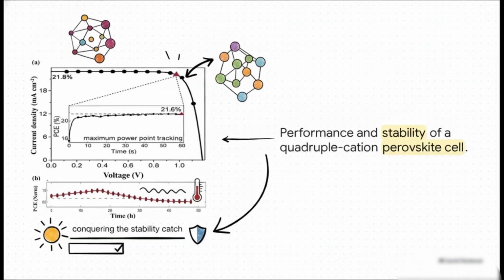And when you bring all of these techniques together, the results are nothing short of extraordinary. Testing a heavily engineered quadruple-cation cell, which basically just means scientists meticulously mixed rubidium, cesium, and 2 different organic molecules to find the absolute perfect lattice structure, reveals incredible stability. Finding that exact sweet spot allowed it to hit a massive 21.6% efficiency. And here's the best part. After 500 grueling hours baking at 85 degrees Celsius under continuous light, it retained 95% of its initial performance. They literally conquered the stability catch.